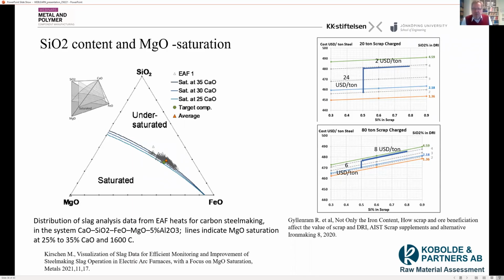So if you have a poor DR pellet, you will get a rather SiO2-rich DRI, and then you will have huge slag amounts. To the right, you can see two examples of what happens in a 100-ton furnace when you have 20-ton scrap or 80-ton scrap. And you can see how much you save or lose when you go from 2% of silicon in the DRI to 4% of silicon in the DRI. It's a huge amount, and perhaps you will see in the future the 100% DRI companies, or the typically 80-ton DRI companies, will try to use more scrap. That will affect the foundry market. In the next decade, there will be a change.